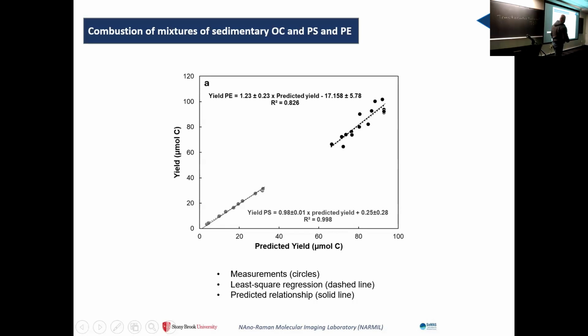So if you see here, when you increase the amount of plastic, of course, the carbon yield increases. What you see here is from zero, pure sediment, to pure plastic. We tested another polymer, because we had only one polymer and wanted to know what happens with other polymers. It's kind of the same. We have more scattered results here, but our measurement falls very well with our predicted relationship, with an R squared of 0.8. So starting with this, we know now that our equipment, our technology, is measuring this.